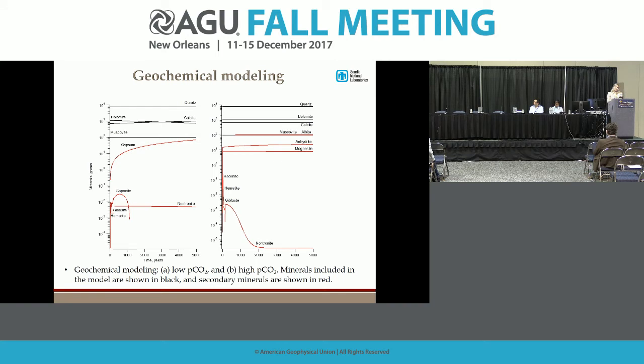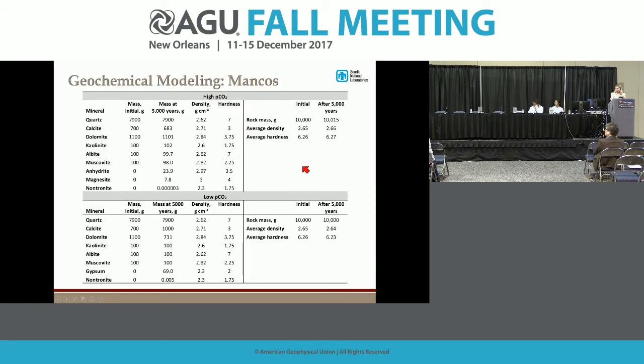And to be able to extend those results long term, we created calibrated geochemical models. We used our observations from the lab to construct these models, but we extended them to 5,000 years, so roughly the duration we would need for geological carbon storage. Again, on the left is the low pressure CO2, on the right the high pressure of CO2, and I'm showing the percentages of different minerals in the system. We're capturing de-dolomitization and precipitation of gypsum in the low pressure, and anhydrite and magnesite in the high pressure system.